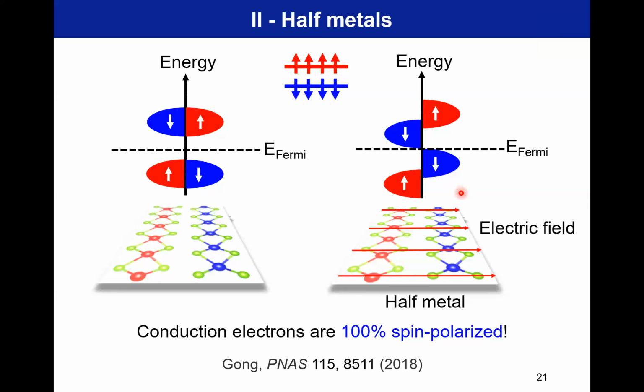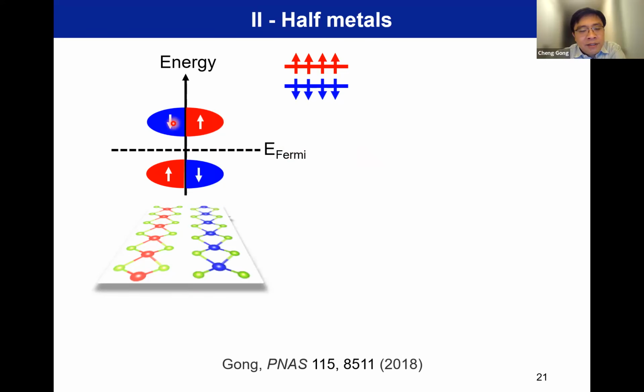Because generally one could anticipate that there's a strong hybridization of electron orbitals from different layers, which may contribute substantially to the formation of the two-layer band structure. So yeah, I was just asking, I have no idea. I think you're right, it is a strong effect. Even for molybdenum disulfide, I think the single layer quasi-particle band gap may be around 2.2 or 2.3 eV. When you merge them, they will have at least another 0.3 to 0.5 eV reduction. But even though there is a reduction, like I put in the picture here, you can imagine the overall gap just becomes smaller, but this relative spin orientation still holds, right?